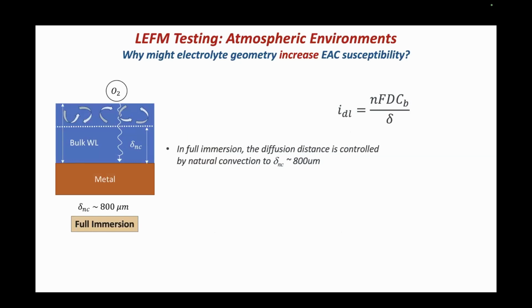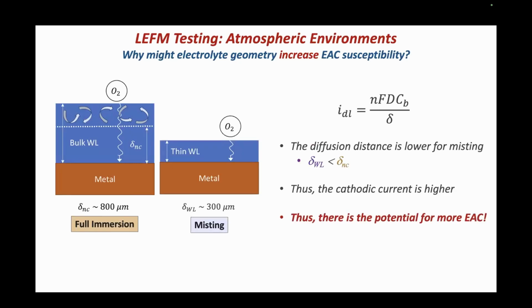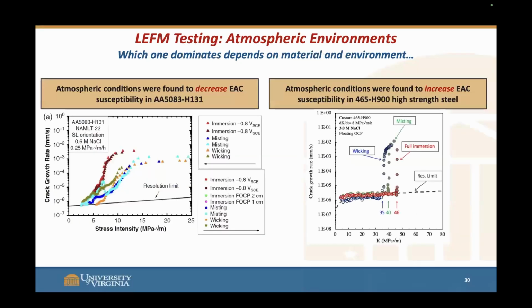And so in full immersion, that diffusion distance is controlled by natural convection. But if we go to misting, it then is going to be just controlled by how thin the electrolyte is. And thus that cathodic current is going to be higher because of more oxygen supply, and thus we'll get more. There's materials that have shown both.